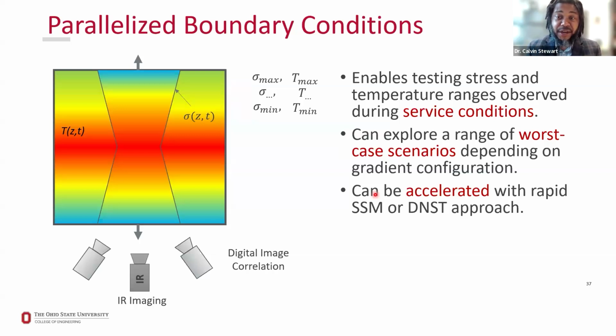Now, finally, we've even thought, well, hey, if we're parallelizing a few things, what if we just parallelize them all? From a quasi-static temperature gradient to a bell-shaped sample where we know the force to a functionally graded material. Could we use this to do A/B testing between one material and another? Or could we use this as a screening test where we're trying to design a material for a specific range of stress and temperatures, and we want to determine for those specific conditions, is this material strong enough? Would it survive? Well, we can make these extreme torture tests for specific applications.